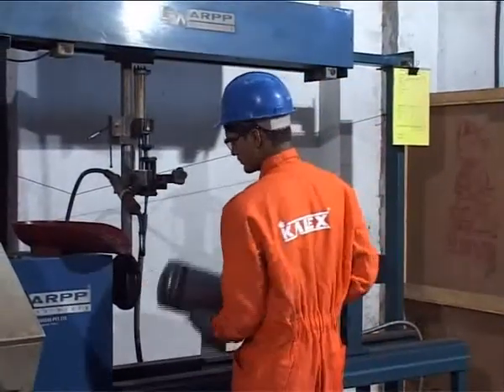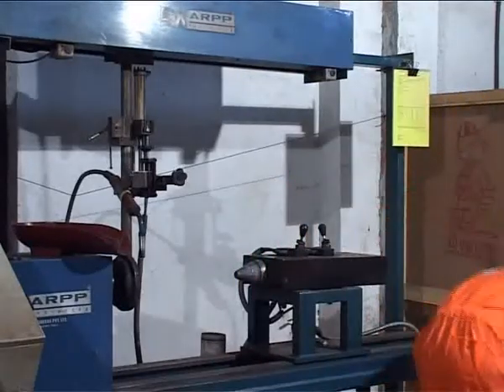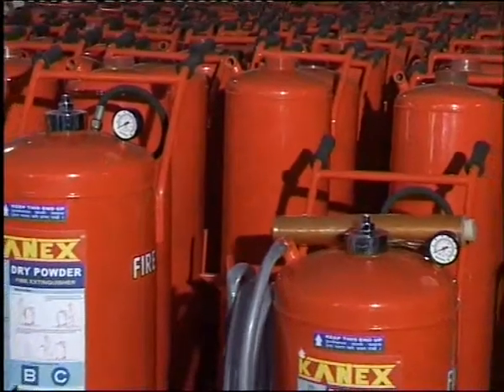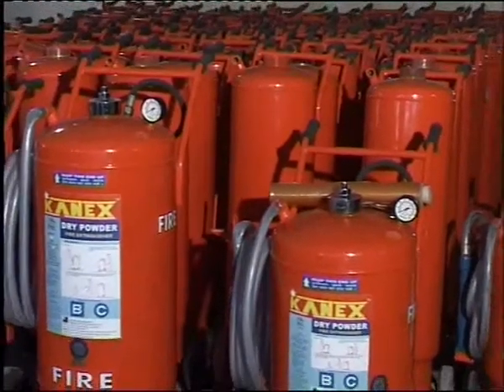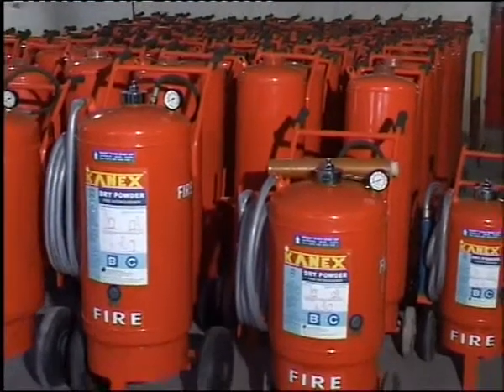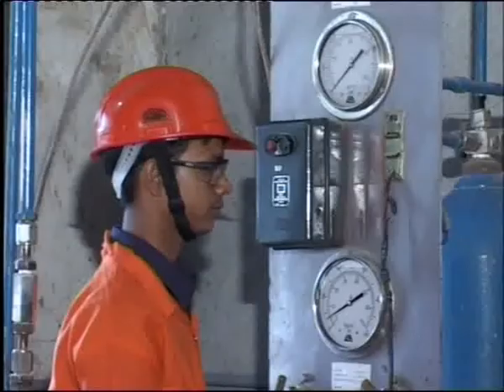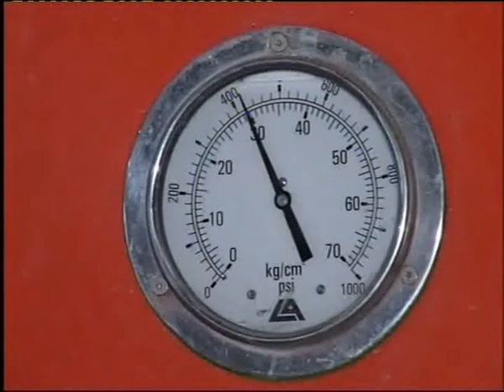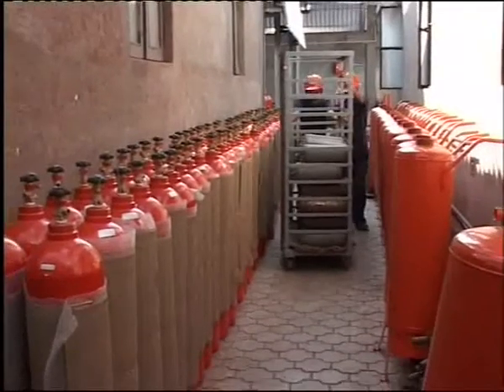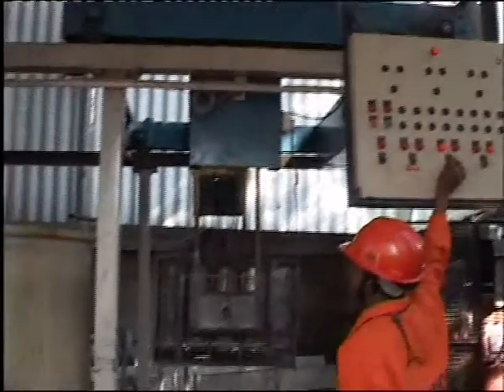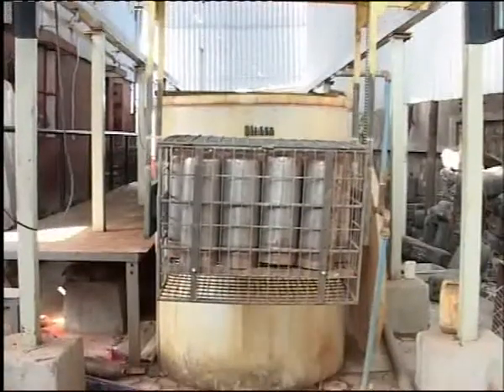Our welding process specifications are approved by Tata Project. We produce fire extinguishers as per applicable standards IS 2825. The welded bodies are hydraulically tested at an internal pressure of 30 kg per cm2 and are randomly chosen for the burst test and the ultimate failure test. Precisely welded cylinders are thereafter taken to KANEX's state-of-the-art auto anti-corrosive treatment plant, which is equipped with a 7-tank hot phosphate treatment, giving better end results of powder coating.